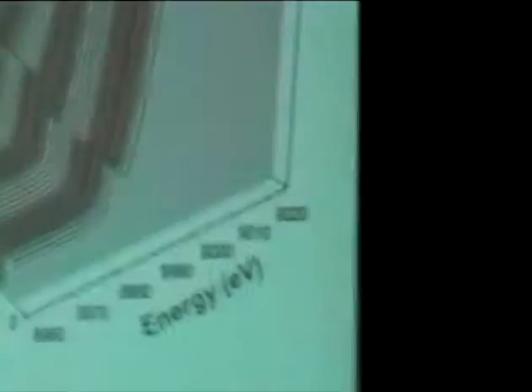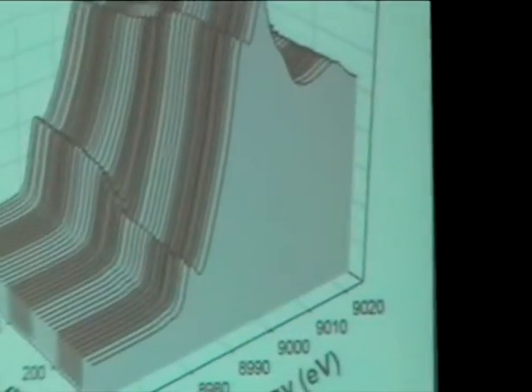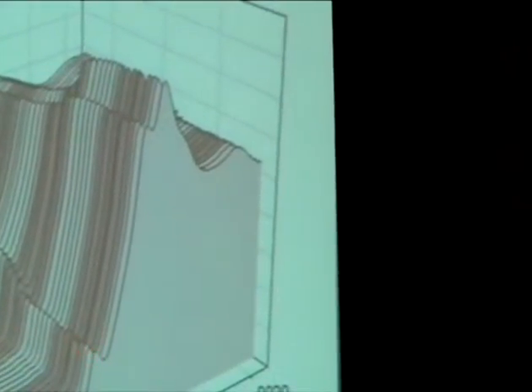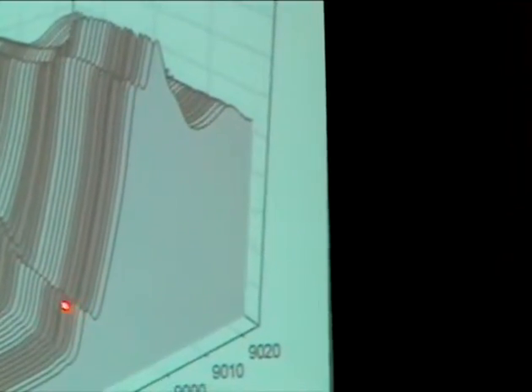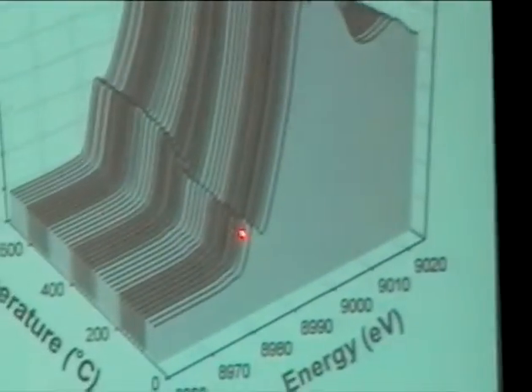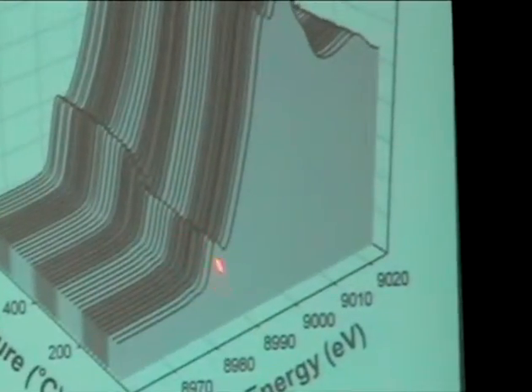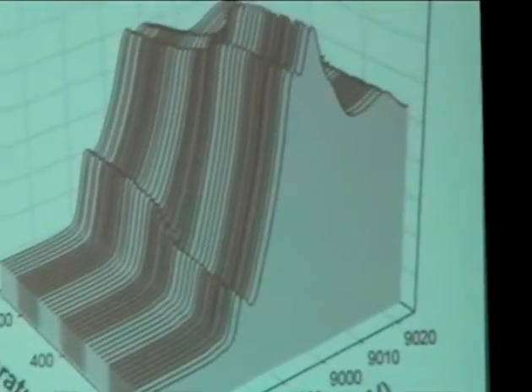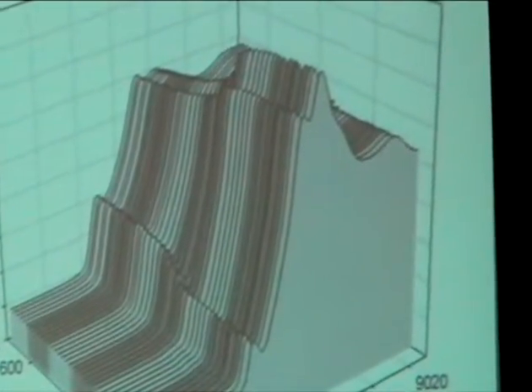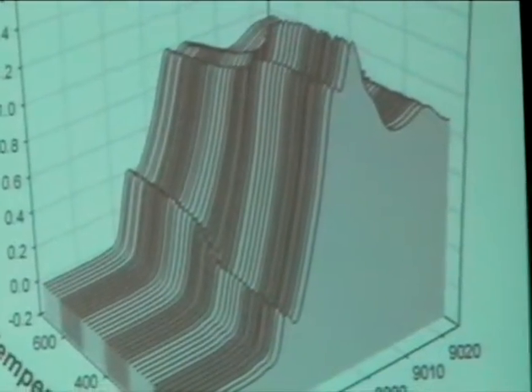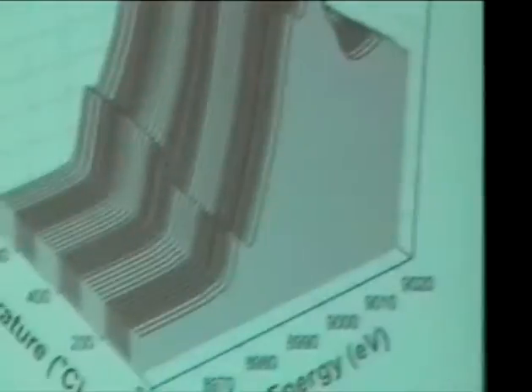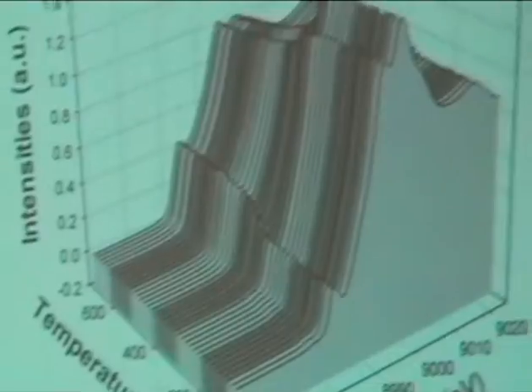If we go over to the overcoated material, which is on the right here, notice a couple of things. First of all, we start out with some of the oxide material that is already reduced. That's that pre-edge feature there. We believe that we've seen cases where the overcoated material using ALD actually is a strong reductant. And we believe that where the overcoated alumina is covering over the copper, it's already reduced that material.